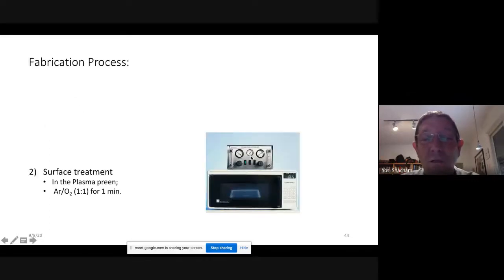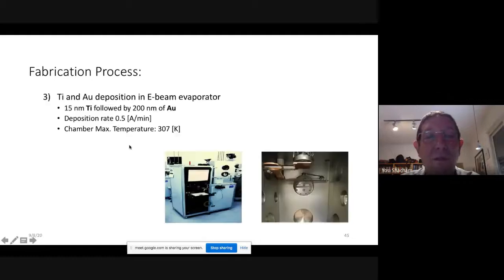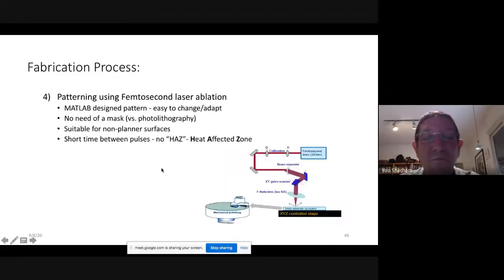Next, we clean the surface with oxygen plasma. Next, we put titanium and gold on top of it. This is our e-beam evaporator. Then we have a substrate with gold and titanium on the polymer, and the laser beam is ablating the metal. And the nice thing is the following. At this wavelength, the PDMS is transparent, but the gold is absorbing. So we can pattern. And because it's a femtosecond, there is no heat diffusion.